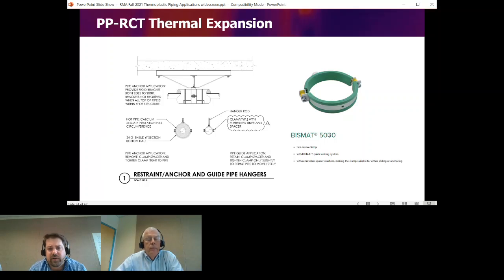Anchors are very similar to what you'd see in steel and copper systems, but they're much lighter and less robust. Basically, the forces from expansion on the plastic piping that you need to restrain are orders of magnitude less than for steel and copper systems. You really just have to clamp down tightly on the piping. They do make specialty types of anchors and guides that can do dual purpose. For example, this is